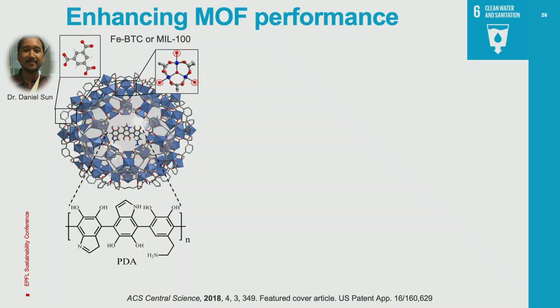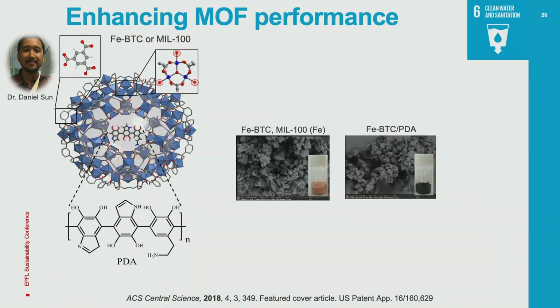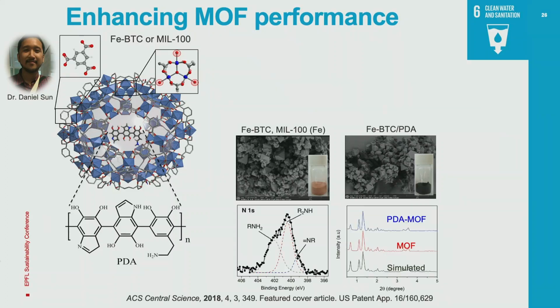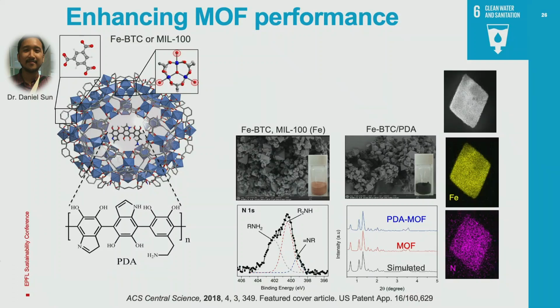So here is our material. I won't go through it, but I will show you its performance. So we put a monomer inside, it cross-linked. We saw an immediate color change of the material, which is due to the polymerization process. Then we can see from our analysis that the polymer is actually forming in the pores. And if you take one of these particles, you put it in an epoxy resin and you just slice it, you see iron, which is a signature of the MOF, but then you see the nitrogen, which is a signature of the polymer. It is throughout the particle. So it tells you that it's definitely diffusing into the pores and forming the polymer.